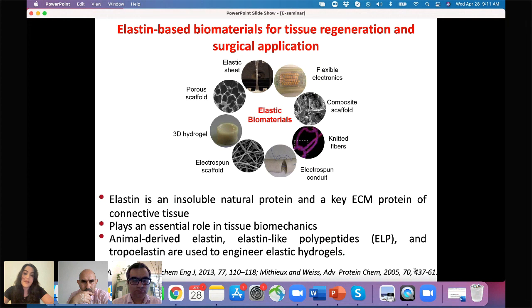tissue in a body. As you may know, elastin is an insoluble natural protein, and it is the key extracellular matrix protein of our connective tissue. It plays an important role in tissue biomechanics, but one of the problems with elastin is that it's insoluble. So in order to form elastic hydrogel, we should use soluble form of elastin, including animal-derived elastin, different sequences of elastin-like polypeptide, or the monomer of elastic fiber, which is called tropoelastin.